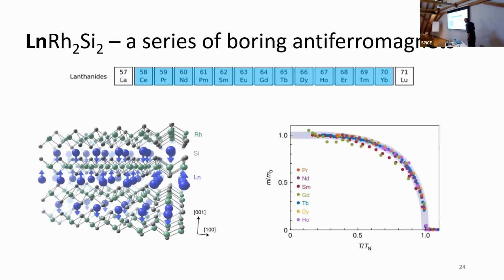What happens essentially is that you heat up the system and the ordered moment goes down and goes away almost identically in all the systems, except for this green and red, which I can explain later. It's a mean field issue. But apart from that, when you take neodymium and replace it with praseodymium, the only thing that happens is that you get a different Néel temperature. Apart from that, the spin structure stays the same, the magnetic structure, essentially. The crystal structure stays the same, and it's all extremely boring. There are no special phases or anything.